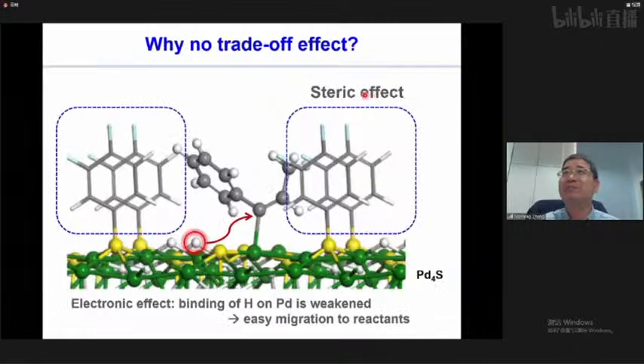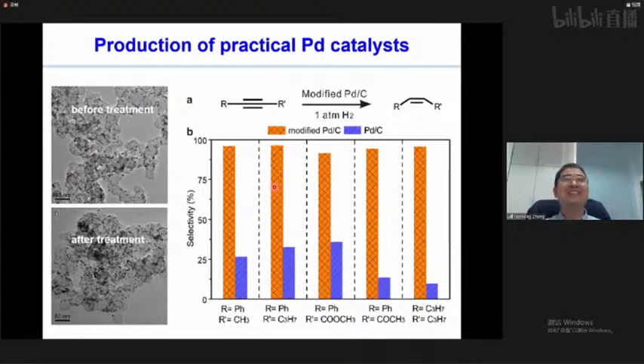The main reason for that, based on our DFT calculation, is that we have the formation of palladium sulfide, and this palladium sulfide species can weaken the bonding of hydrogen on palladium. Which means that this hydrogen species can easily migrate to the substrate for the reaction. So after this understanding, the whole picture is rather simple. The thiolates create a steric hindrance to prevent the further hydrogenation of alkene, and the electronic structures created by the formation of palladium sulfide promote the catalysis. So we don't have the trade-off between activity and selectivity, right?